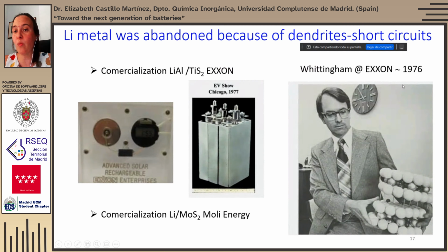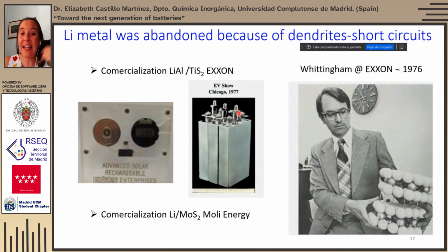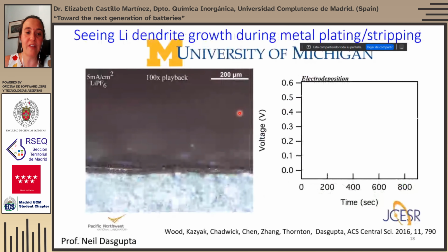Actually, Professor Whittingham, who proposed the lithium titanium disulfide battery in the 1970s while he was working at ExxonMobil, they commercialized their batteries with the lithium aluminum alloy anode, as well as Moli Energy commercialized as well lithium molybdenum disulfide batteries. And they had to withdraw their batteries from the market very fast because there were always problems of short circuit. And this is because of the dendritic growth of the lithium.